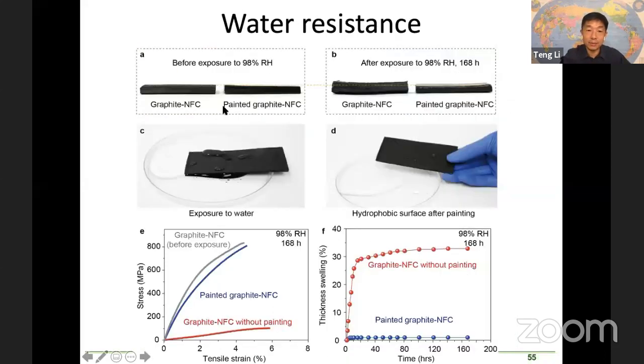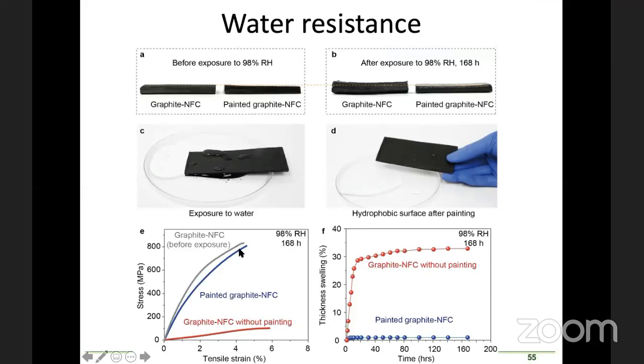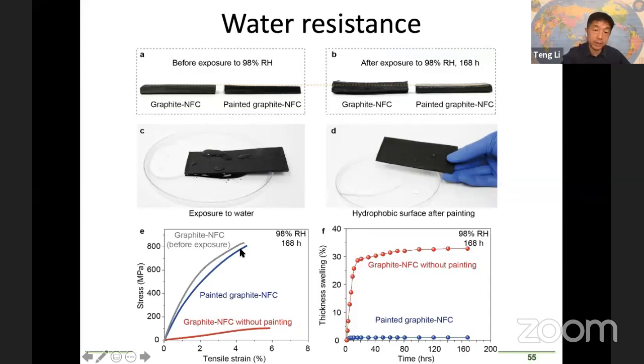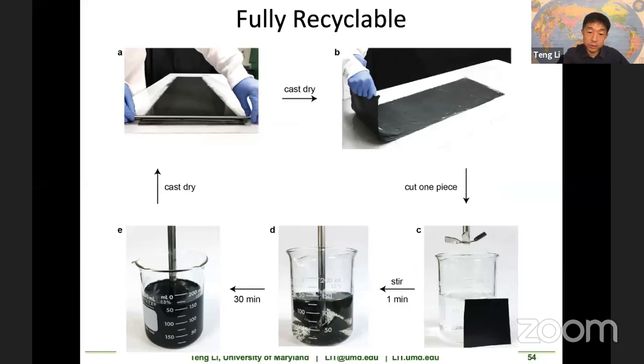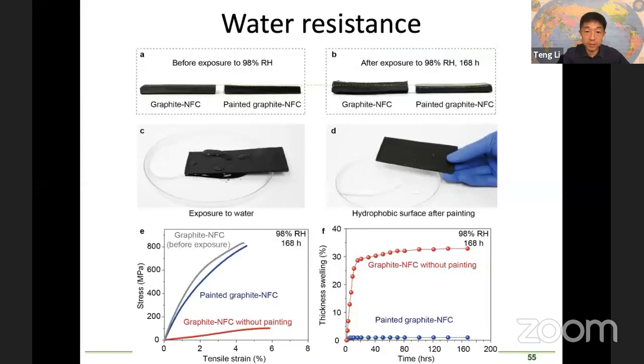To mitigate that, we demonstrate that if you coat the surface of this material with a thin layer of anti-water coating, you can actually maintain the mechanical property in this accelerated test, 98% of relative humidity for 168 hours. This gray line and the blue line are the before and after you coat the thin layer of anti-water coating. So you can mitigate this water stability issue. And this coating is so thin that even if you coat it with this coating, you can go back to use the mechanical stirring to break that layer of coating to allow you to do the recycling use of the material. Okay.